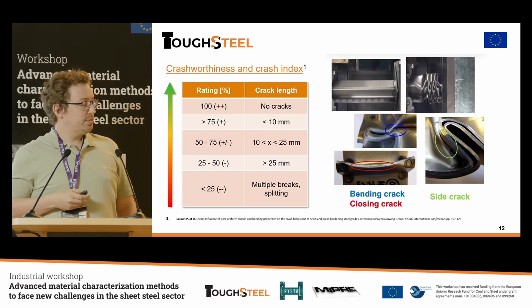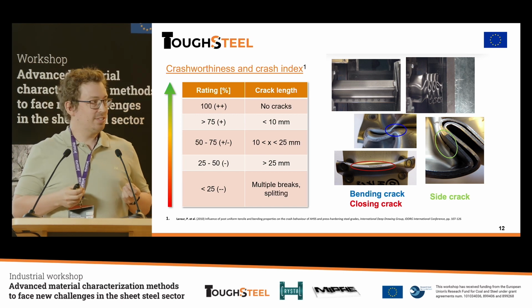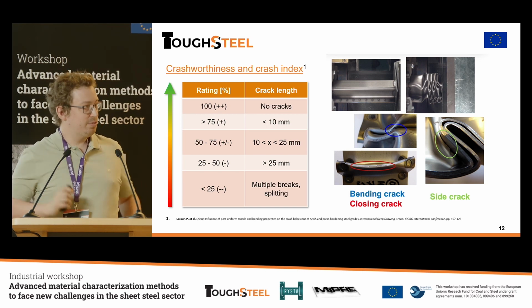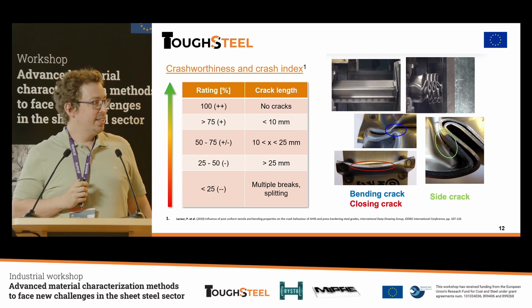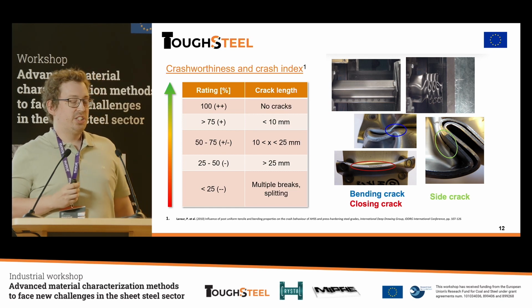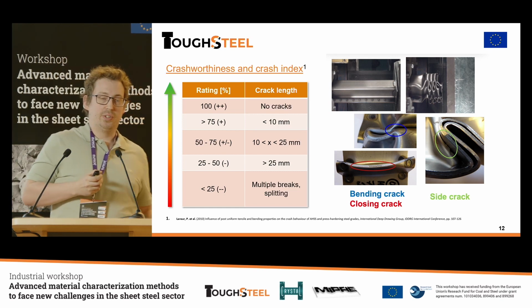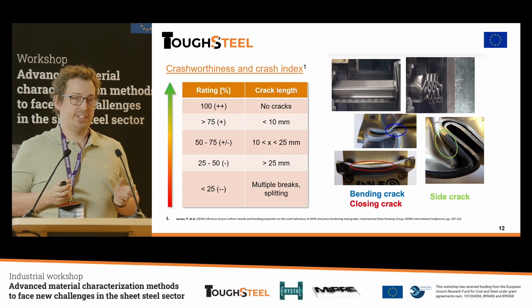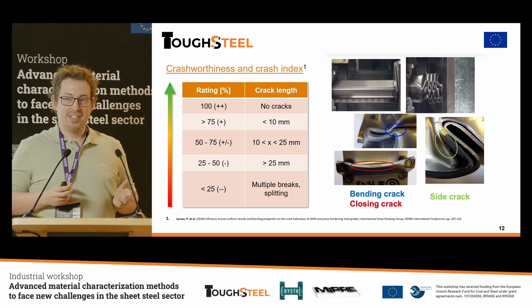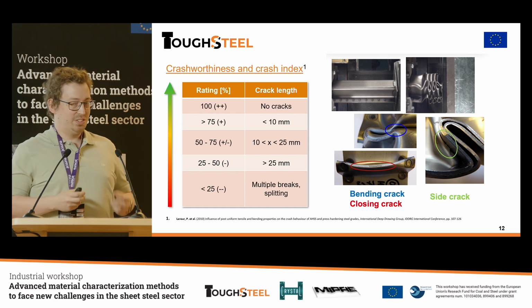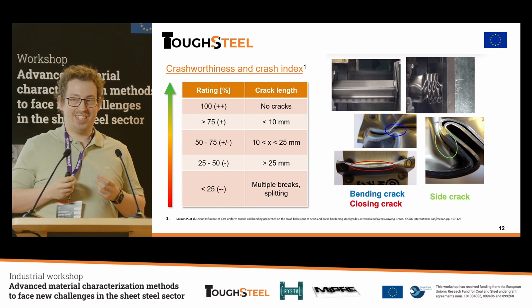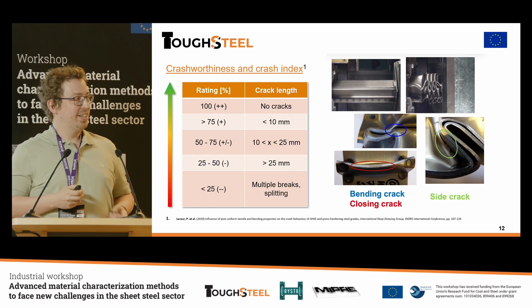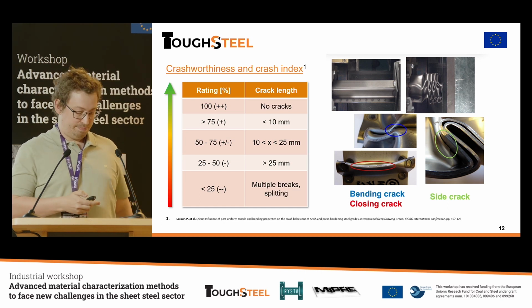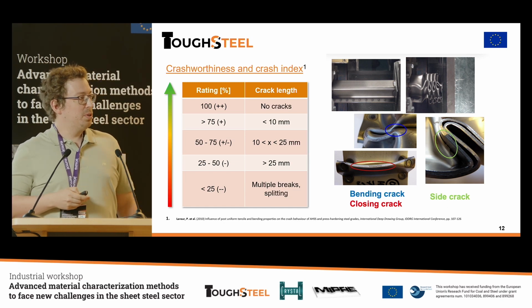Of course, a problem with this is that generally you spot weld these crash boxes to keep them stable for the folding, as you can see here. And when you're evaluating the crashworthiness of a material, you're generally just interested in the bulk material. When you spot weld it like this, you have classic initiation sites for cracks, and it usually starts in these spot welds. So that's a problem with this method.